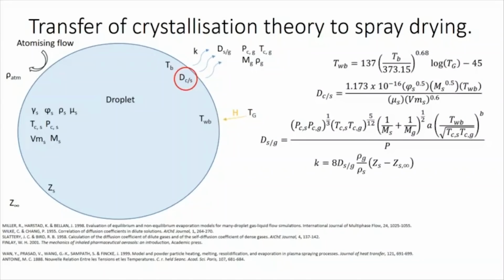made. The ratio of the evaporation rate to the diffusion coefficient of the solute in the solvent gives the Péclet number. This is a dimensionless number for which a value of less than 1 implies that the diffusion of the solute is faster than the rate of solvent evaporation. This will show that there is adequate time for the solute to diffuse away from the drying boundary layer towards the center of the droplet, forming a spherical particle with a solid core.